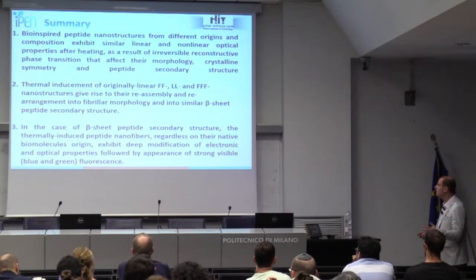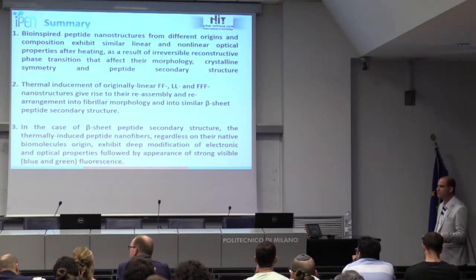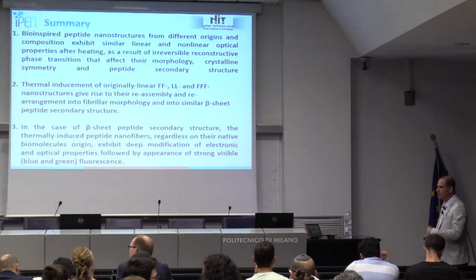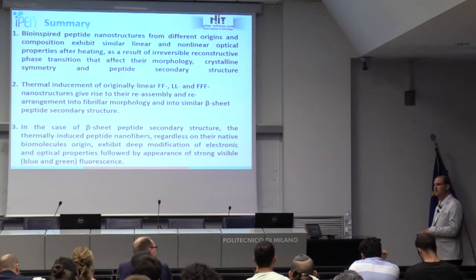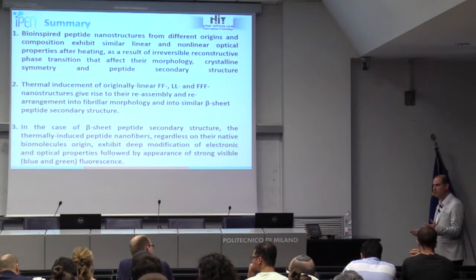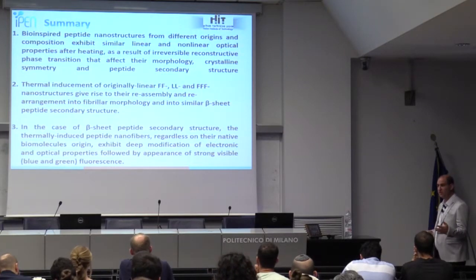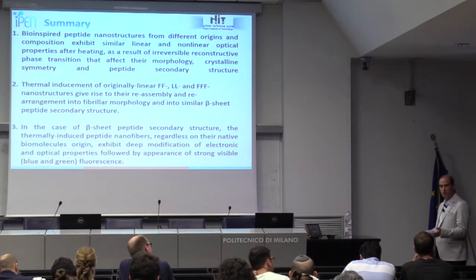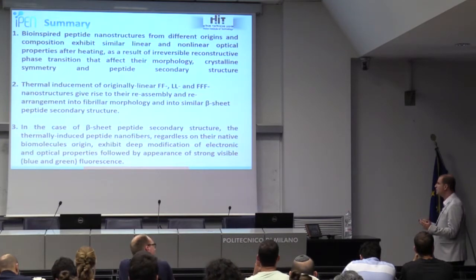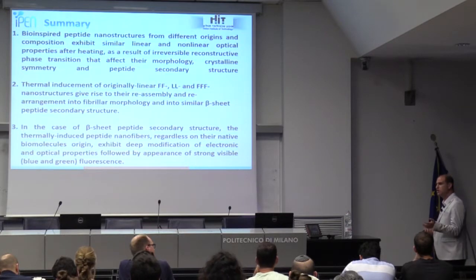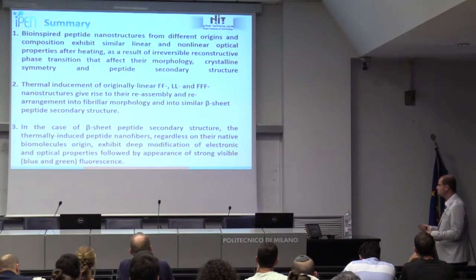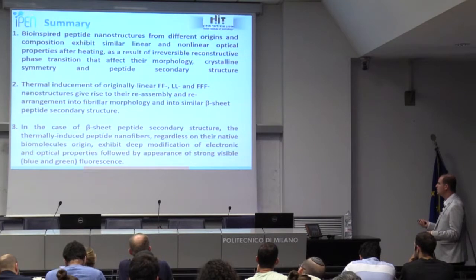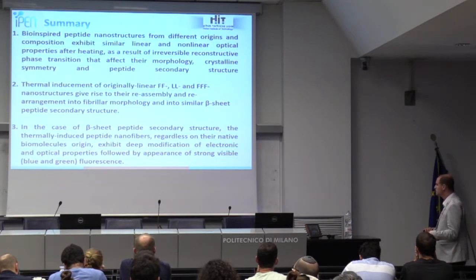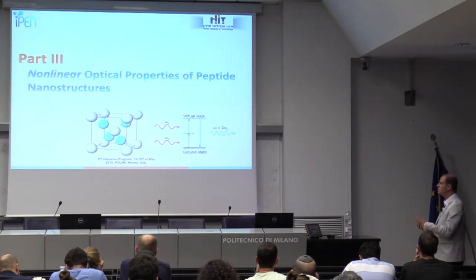So if I want to summarize, I showed you all kinds of morphologies of bioinspired peptide nanostructures. Although they are from different origins, the common thing is the appearance of visible blue and green light as a consequence of heating. The common thing to all of them is the formation of beta sheet secondary structure, which is very rich in hydrogen bonds, which probably causes a reduction in their energy bands. And there is a deep modification of all their electronic and optical properties, followed, of course, by the appearance of this strong visible fluorescence. So this is part 1.